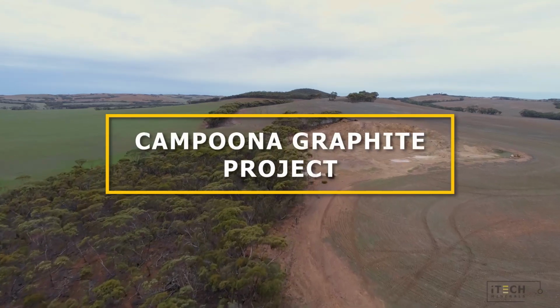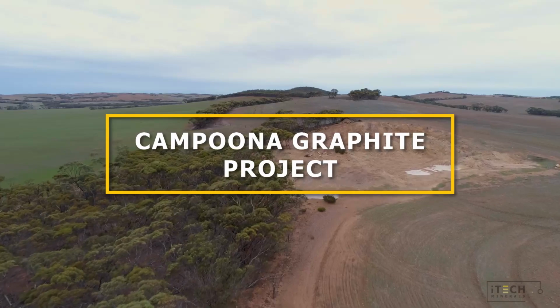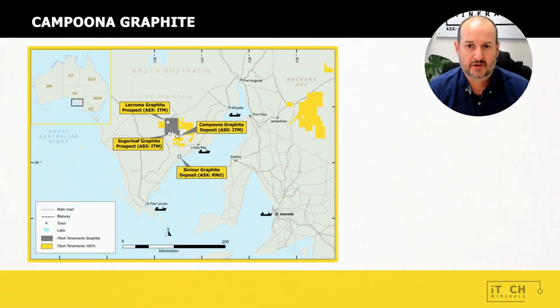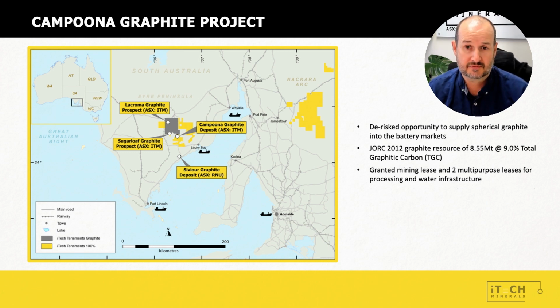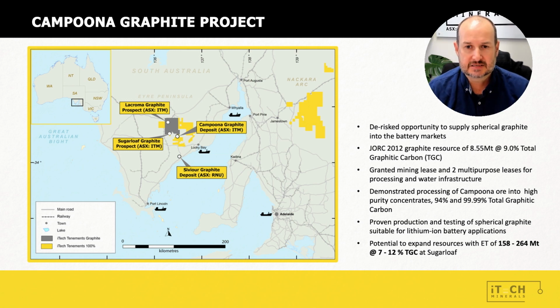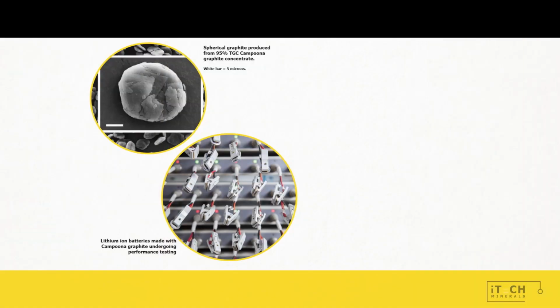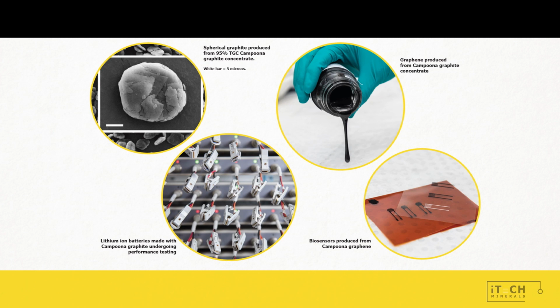So when we started iTech back in 2021, we knew that we had a very high quality graphite project at CAMPOONA on the Eyre Peninsula. We had a JORC-compliant resource of 8.5 million tonnes at 9% total graphitic carbon. We acquired a granted mining lease and two multi-purpose leases, one for processing and the other for water infrastructure. We knew that we could process that CAMPOONA ore into high purity concentrates, an initial flotation stage to 94%, and then a later hydrofluoric acid concentration stage to 99.9% total graphitic carbon. And we also knew that the CAMPOONA ore was of high quality enough to produce spherical graphite suitable for lithium-ion batteries. The graphite's also being converted into graphene and being used in technical applications such as in biosensors.